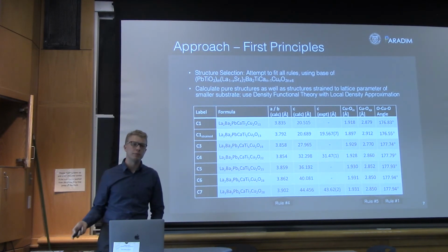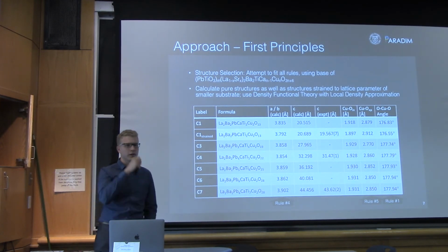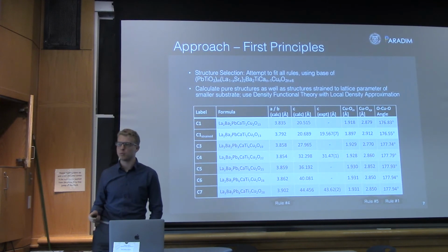Another thing, we haven't optimized the ozone yet, and so we don't know if we have the proper doping of oxygen in the samples. So there's definitely plenty of variables that are still at play. But in general, it's still functional. We still think that if we play around with enough of the variables, we might get there.